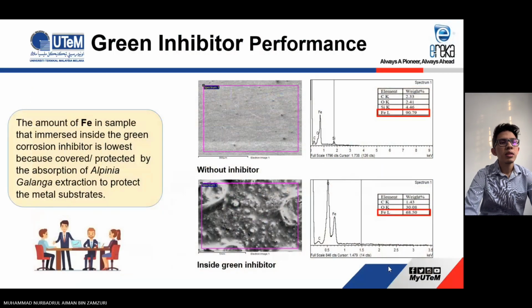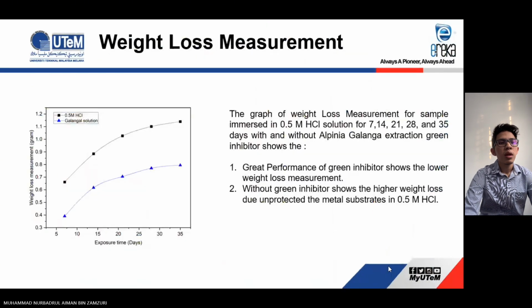Next, these two figures of graph show the comparison of ferrum amount on the low carbon steel surfaces without and inside the inhibitor. The amount of ferrum in the sample that was immersed inside the green corrosion inhibitor is lowest because it is covered and protected by the absorption of Alpinia galanga extraction to protect the metal substrates. As we can see from the plotted graph, we can conclude that the great performance of green inhibitor shows the lower weight loss measurement. Besides, without green inhibitor shows the higher weight loss due to unprotected metal substrates in 0.5 molar hydrochloric acid.